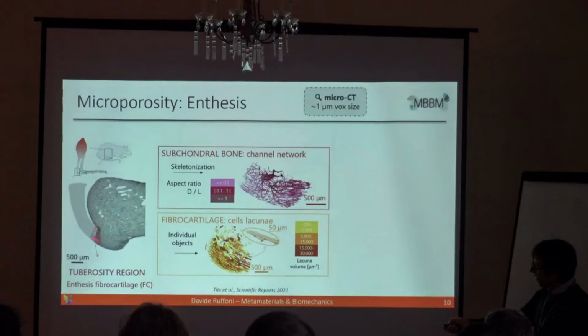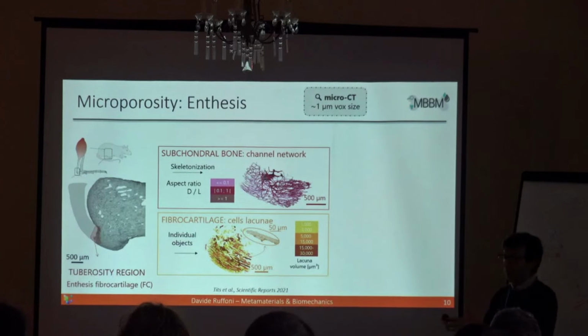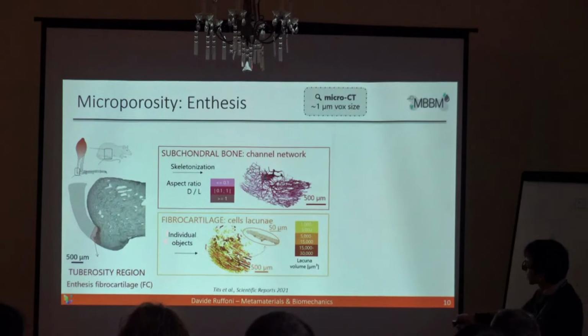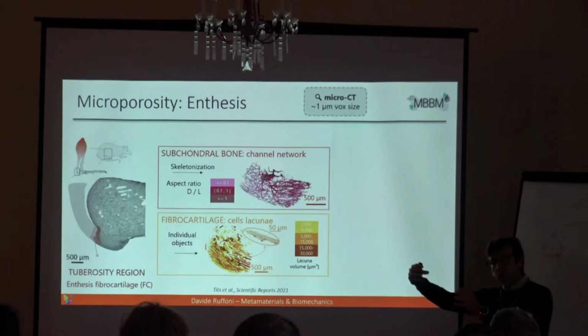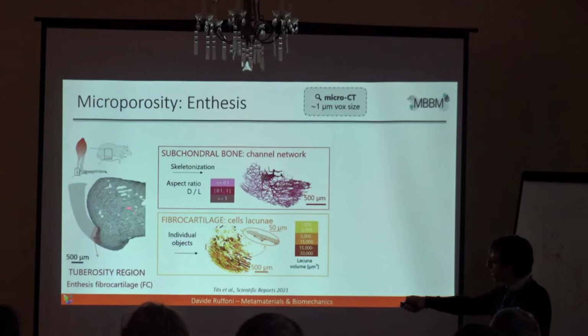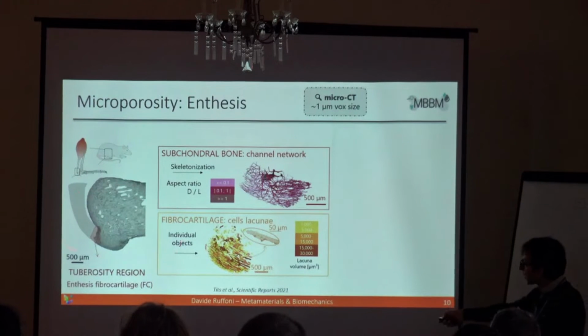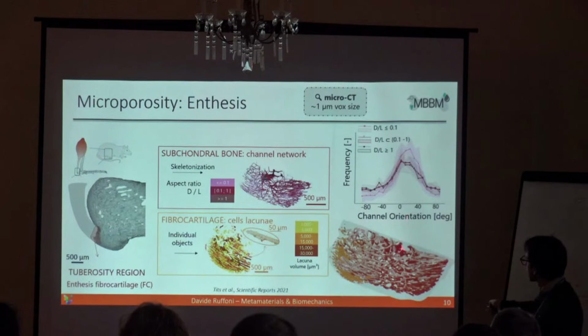And when we do the same exercise down here where the tendon is inserting, we see a very aligned structure. So these are the same bone, two locations which are very close to each other, but which are solving different mechanical functions, and this is reflected in the microscale porosities, because we see, for example, fibrocartilage cells which are well aligned, and also blood vessels in this region which are highly aligned. So the fact that tendon is inserting in bone is reflected in the bone structure hundreds of micrometers away from the insertion point. Or let's put it like this, bone is able to respond to the mechanical requirement imposed by the tendon by aligning its microstructure. So we see some preferential orientation here which matches the insertion direction of the tendon.